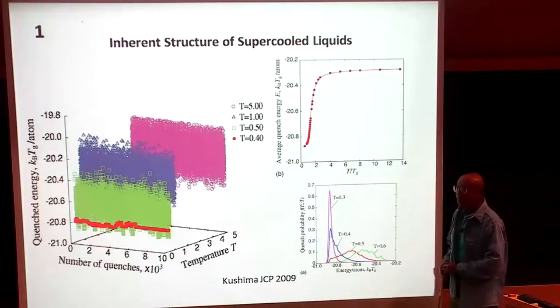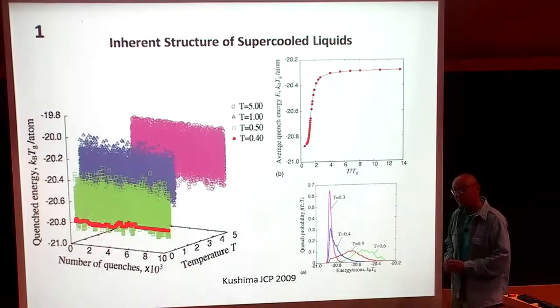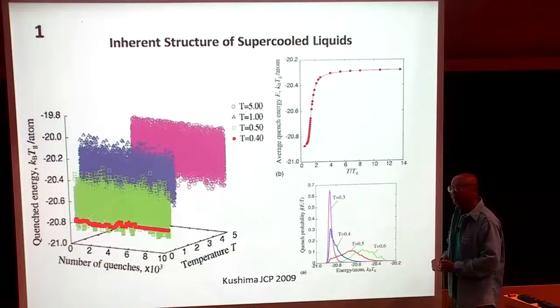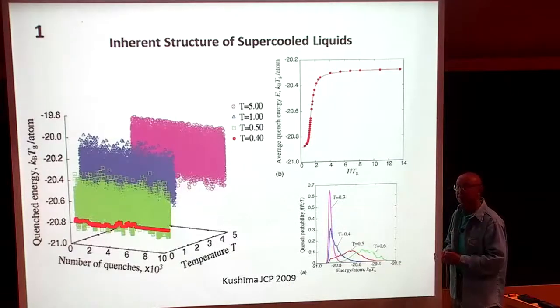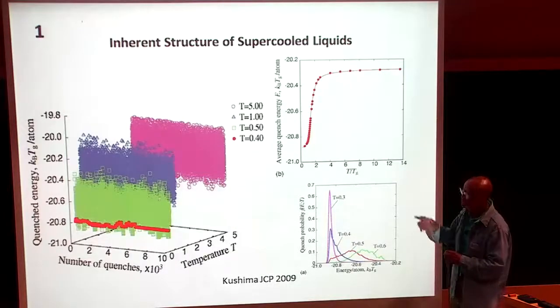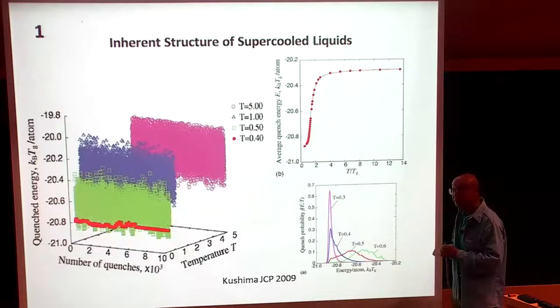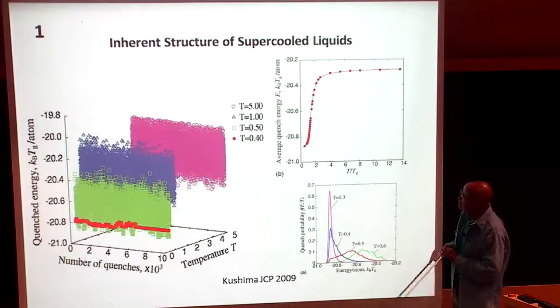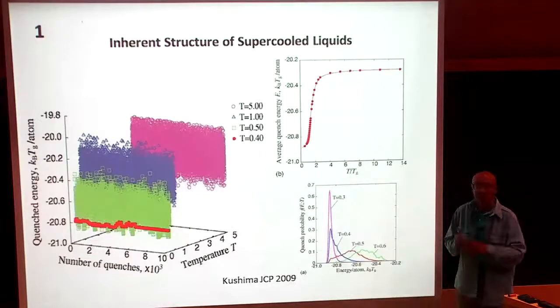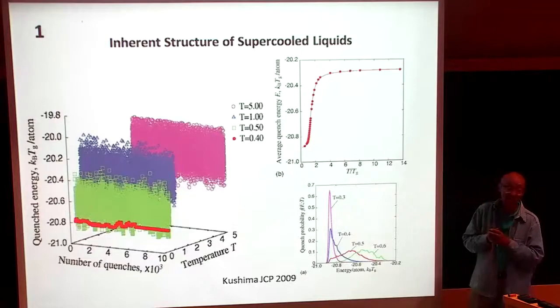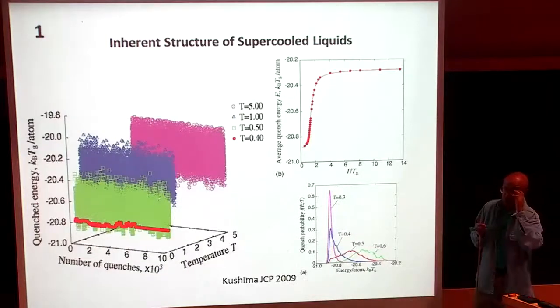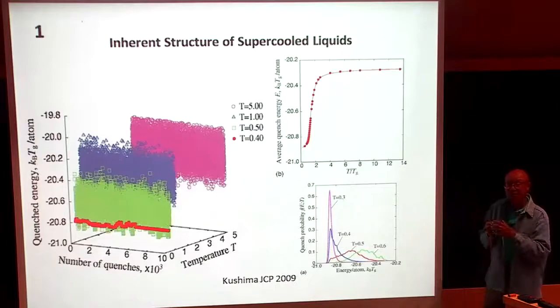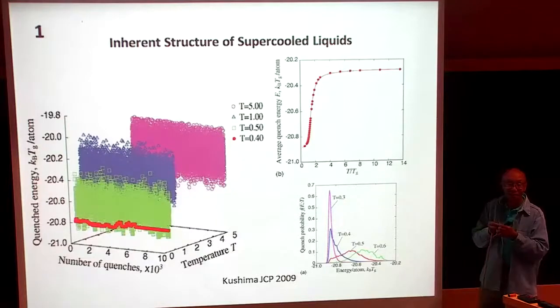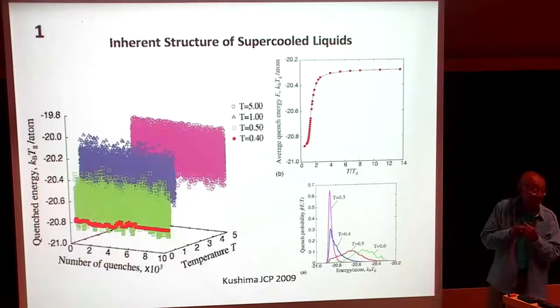Now, Stillinger was at Bell Labs working with Tom Weber, also at Bell Labs, and they were among the forerunners of using MD to probe silicon, for example, and also they came up with a three-body potential for silicon, but along the way they were interested in glasses. Basically what you do is you take a liquid with an interatomic potential, so no fitting is required. Let's say there's something called the Kob-Andersen binary Lennard-Jones potential. It's basically soft spheres of two different sizes.